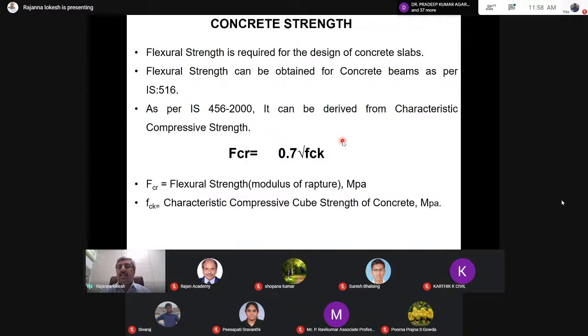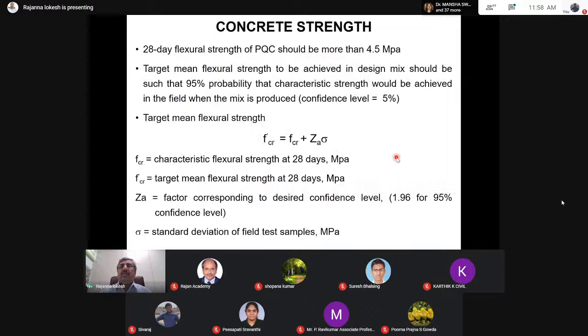If we are going with an M40 grade concrete, FCK will be 40. So 0.7 root 40 will give us the flexural strength of concrete. So in all possibility, the flexural strength of concrete for a PQC of M40 grade is considered as 4.5 MPa. Whereas when it comes to flexural strength, it is all the more important for us to find out flexural strength with respect to target mean strength, which can be arrived using the formula.